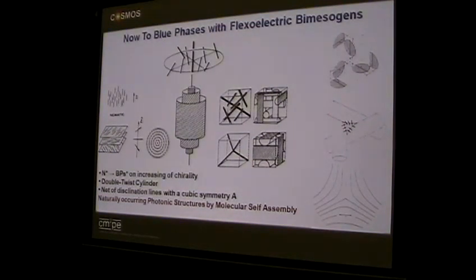We did a whole load of work using fluorosurfactants. Fluorosurfactants don't want to be in a liquid crystal. They want to be at the surface or in an isotropic region. And they will transport to the S equals minus a half disclination, and they stabilize, as I showed you, the blue phase. So what I wanted to point out is we're actually using naturally occurring, or you can just synthesize them, photonic structures that self-assemble and give you three-dimensional photonic band gaps, as you will see tomorrow.